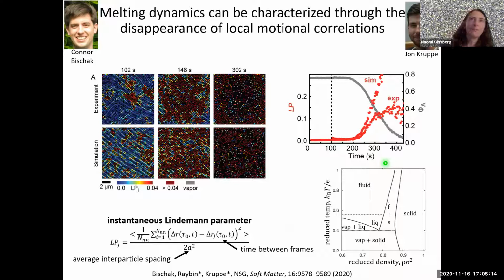Okay, so this instantaneous Lindemann parameter was really essential to refine the match of simulation and experiment. So first, looking in aggregate, like over the entire region of interest, shows correspondence of the divergence. This is a much more stringent test than just looking qualitatively at the images. It also pinpoints the specific trajectory that the system takes on the phase diagram. So it turns out to be consistent with a supercritical transition from solid to fluid.